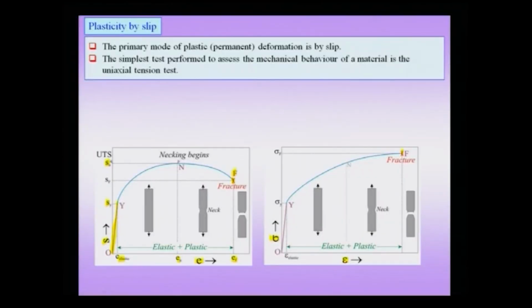Now, the important things to note from this curve are, initially there is a linear region in this curve, which we call the elastic region, and there is a corresponding elongation, which is now my elastic elongation given by this value E u. Now, the value of E u and epsilon elastic is very similar, because in small strains I can actually use the engineering strain as well as the true strain, and they are equivalent. Only when the strains become large do I have to differentiate between engineering strain and true strain.